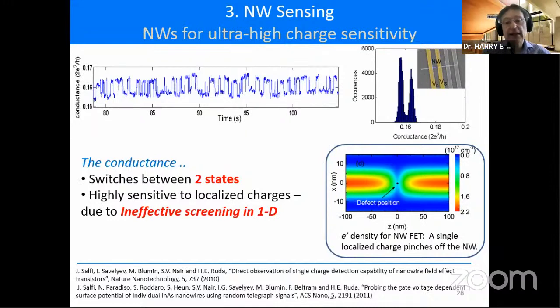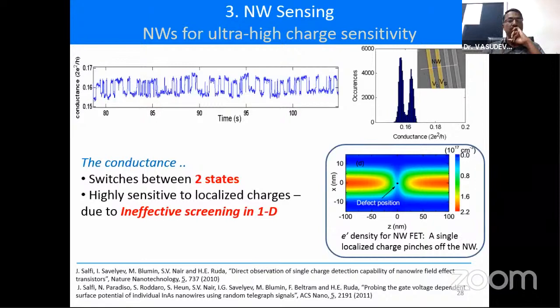All right, so that's the end of my discussion of optical paradigms within the nanowire regime for sensing, what we've looked at. Now I want to talk about a different approach, which is the electrical approach. And the idea here is shown in the top right figure insert. We're looking here at a single nanowire, and that single nanowire is disposed between two gold contacts, and underneath that structure is a silicon dioxide on degenerately doped silicon base. So that's an FET, a field effect transistor. We can modulate the channel conductance by modulating the potential applied to the silicon backgate, and we can measure the conductivity as current flows through the nanowire.